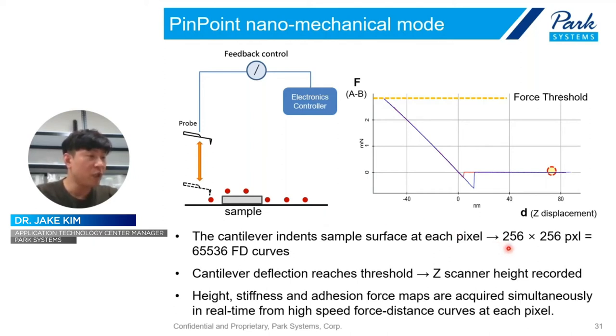For example, let's say 256 by 256 pixels, it means the system performed the FD curve around 65,000 times. And they collect every single piece of information, including mechanical property and height image, and then make an image of each channel. So we can check the imaging of height and mechanical properties. Like this, one FD curve and move to the next pixel. FD curve, FD curve, FD curve. Measure the whole area.